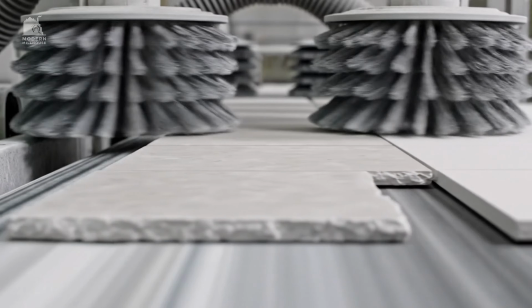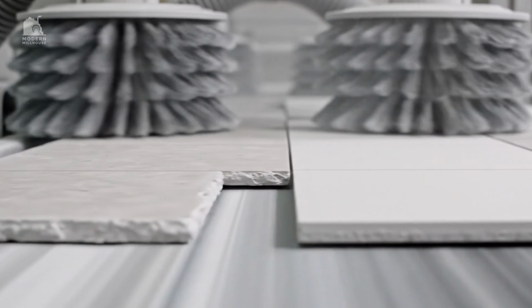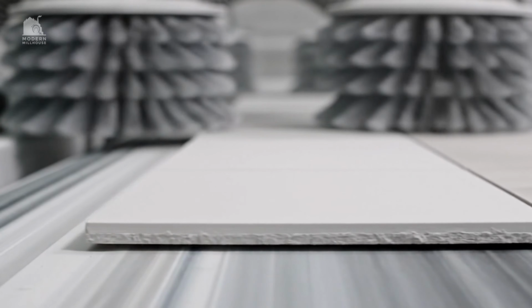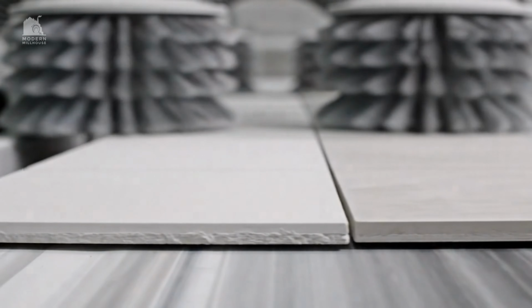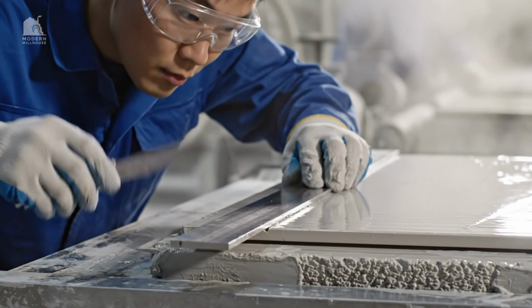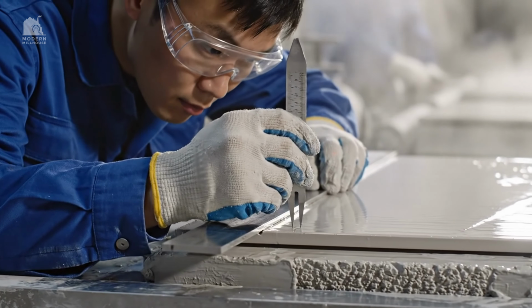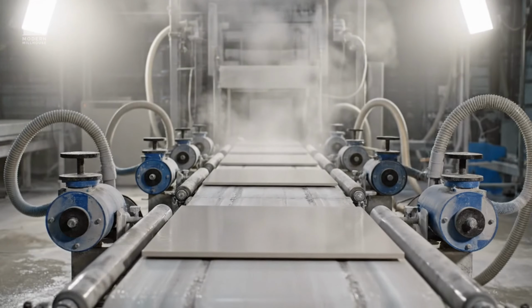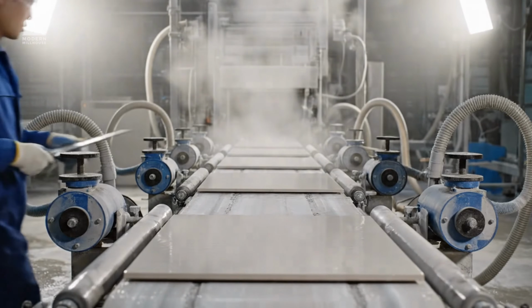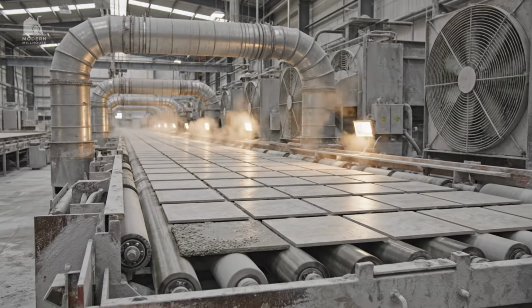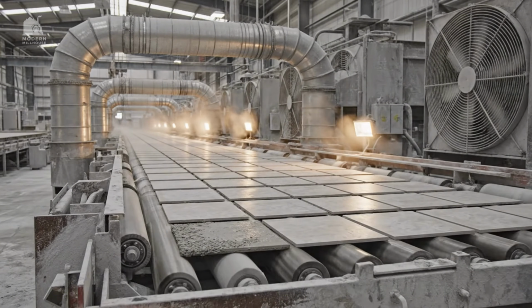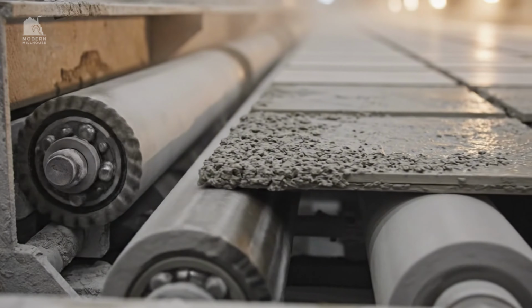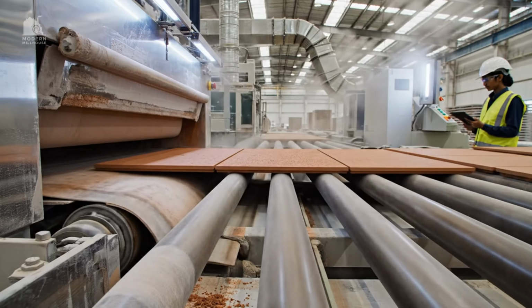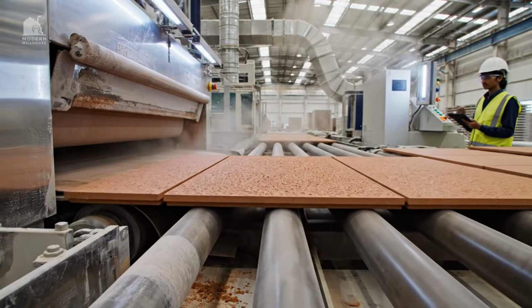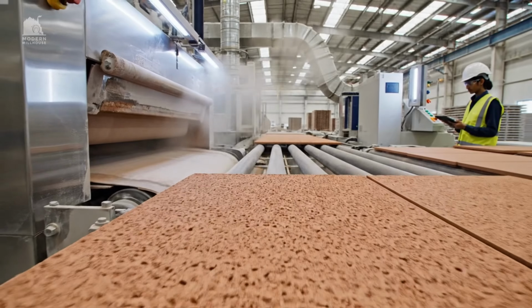Pressed tiles still contain moisture from the spray-dried powder. That moisture must leave before firing, or it will turn to steam and rupture the body. Drying sounds simple, but it is one of the main causes of warping if done carelessly. If the surface dries and shrinks faster than the core, stress builds and the tile curls.